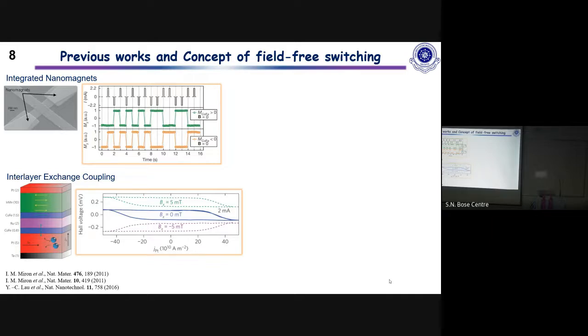So before our work, actually, people tried to break this rotational symmetry by several different techniques. I would just list two of them. The first is they took an island. So this is a nanomagnet. This is a cobalt platinum layer, and they basically made these lithographically patterned magnets along these two sides. And these lithographically patterned magnets were a source of in-plane magnetic field. And this in-plane magnetic field then broke the symmetry and it gave rise to the deterministic switching.